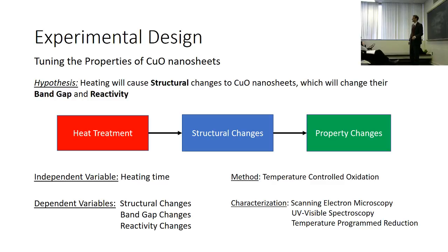I heated it for different amounts of time—30 minutes, 60 minutes, 120 minutes—in oxygen, because I didn't want to change the composition. I wanted it to still be copper oxide. Cupric oxide is the most oxidized form of copper you're going to get, I thought—we can get back to that later. So that was the plan. Then I was going to measure the band gap using UV-Vis and the reactivity using TPR. I'll get to what TPR means in a second.